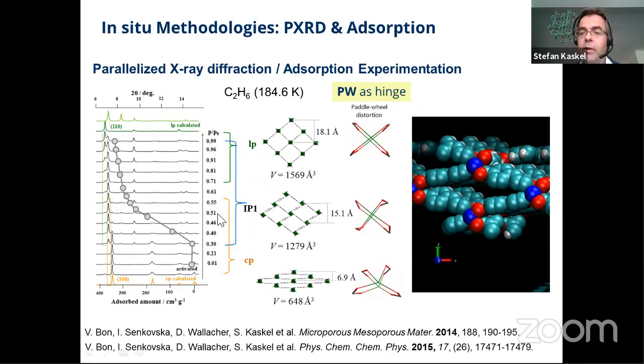And you can analyze all the X-ray diffraction patterns by Rietveld refinement or simulation and find out what is the structural transformation. And what you recognize here is that this is the ideal paddle wheel, and this is the highly distorted paddle wheel in the closed pore phase. So here, the paddle wheel is the hinge. So that's the flexibility mode. The paddle wheel acts as the hinge in this type of transformation. And here we have a two-step gate opening, basically, and the hinge is slightly opening up.